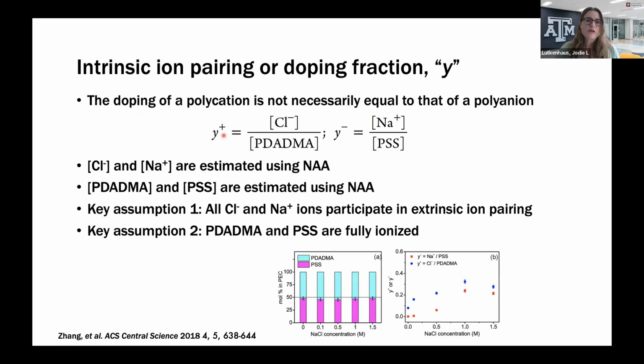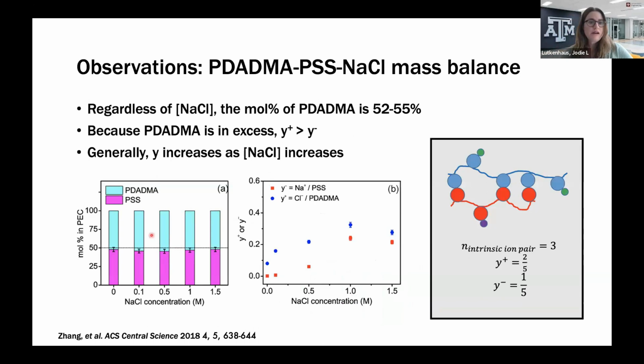There are actually two doping levels, one for each polyelectrolyte. The polycation may be doped to a different degree from the polyanion, and we can measure and quantify this using neutron activation analysis. This is the equation for how we do that. We have to make certain assumptions to move forward with the calculation. We have to assume there are no co-ions. What that means is that any ion we detect, we assume it is associated with an extrinsic ion pair. And then we also have to assume these two polymers are fully ionized. From that, we can get the mole fraction of PDADMA and PSS in the complex, and then the doping levels.